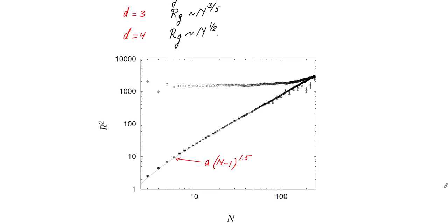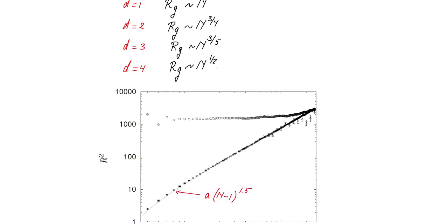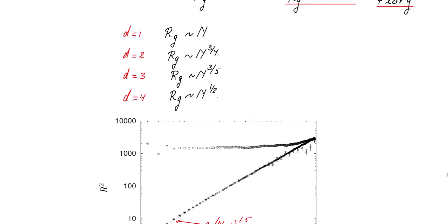So we have seen a very powerful way of calculating the scaling behavior of the radius of gyration of a polymer in which the beads do not want to overlap. This is known as the Flory exponent or Flory theory. We have checked the Flory exponents for different dimensions. Linear in one dimension, three quarters in two dimensions. You can see that here in the result of this simulation. I don't have a simulation for three dimensions, but also there the agreement turns out to be quite accurate. And in four dimensions, we cross over to the non-interacting chain, a Gaussian chain or a free chain.